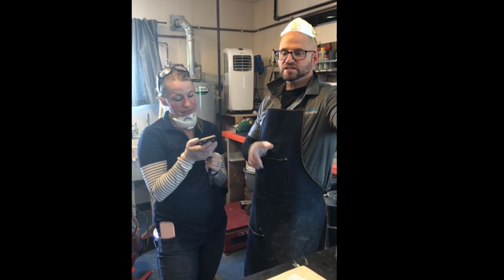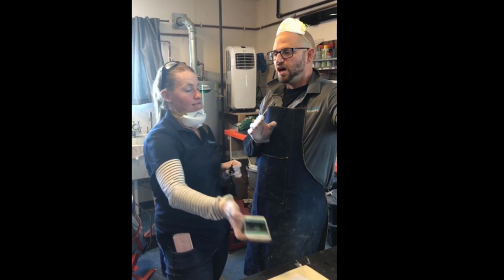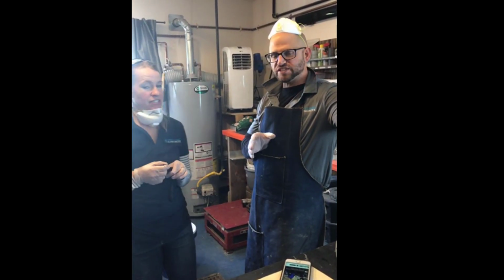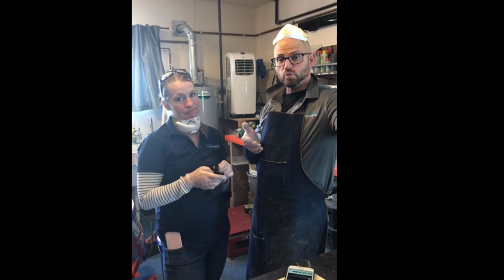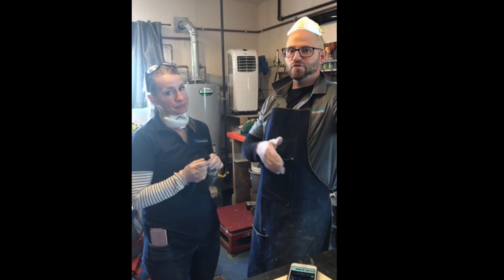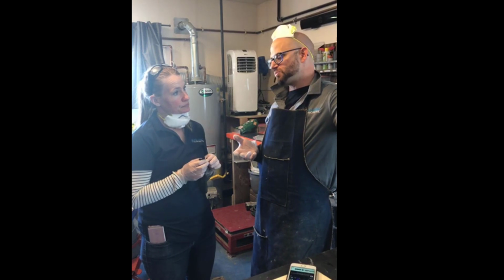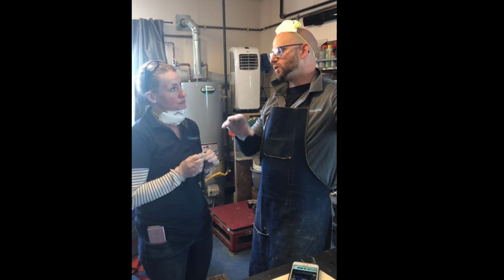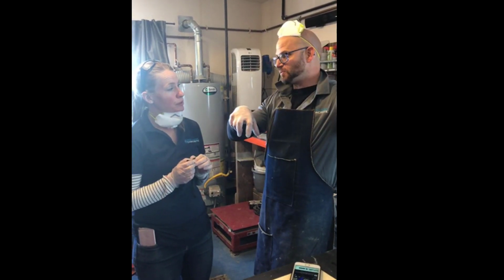But why didn't you slice the specimen with the electrical saw? So what El Khalil is referring to is a video that we did on a modified version of ASTM C1585, which is a capillary absorption test. A wicking test. What that test does is it's basically a mass gain test. Over 7 days, you're working with a dehydrated piece of concrete, and you're identifying the primary and secondary absorption of the water into the concrete. And like I said, you're just weighing it every so often, and it's sitting on top of water.